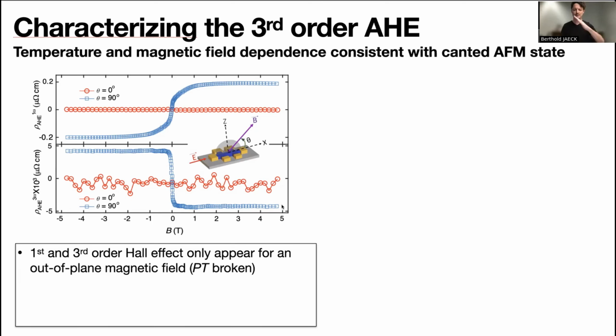Now, when we rotate the same sample to be parallel to the magnetic field direction, meaning the field is pointing along the in plane direction, we do not observe a third order Hall response, except some noisy background. And this is exactly consistent with our expectation that a field would be needed to essentially break the PT symmetry by slightly canting the spins.